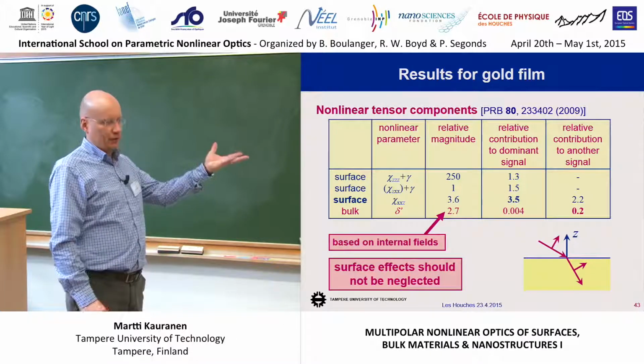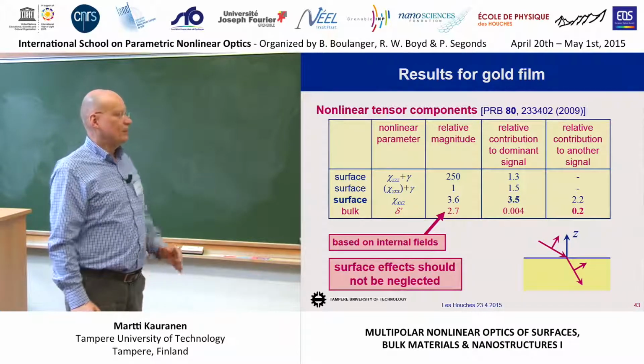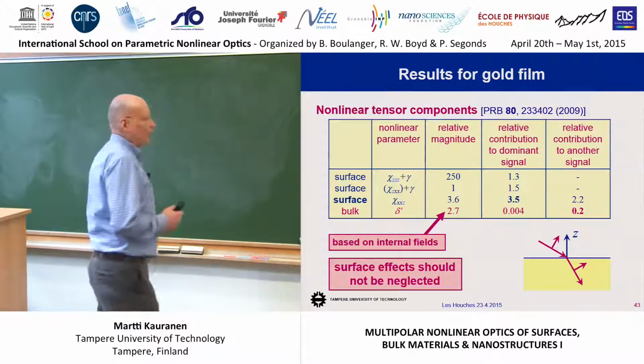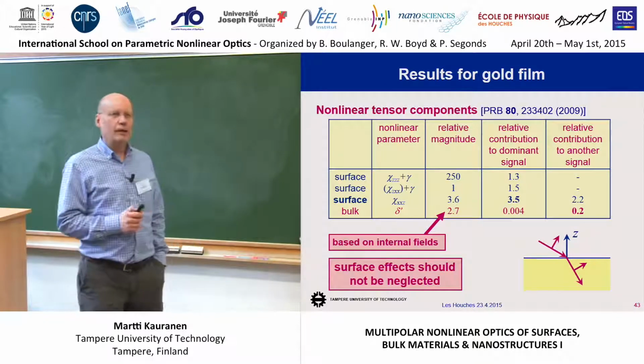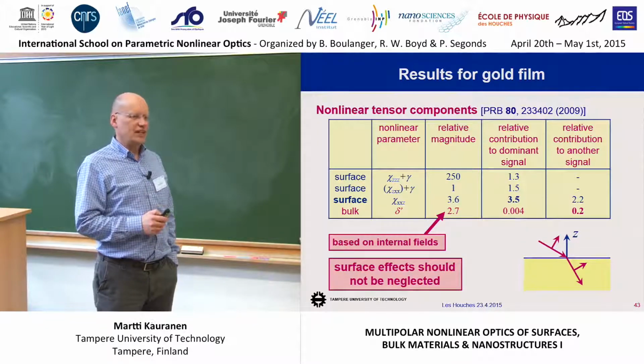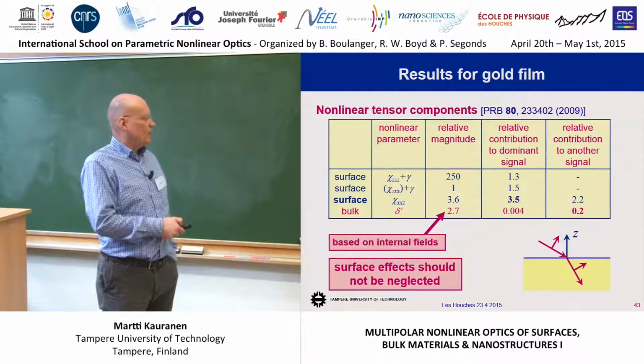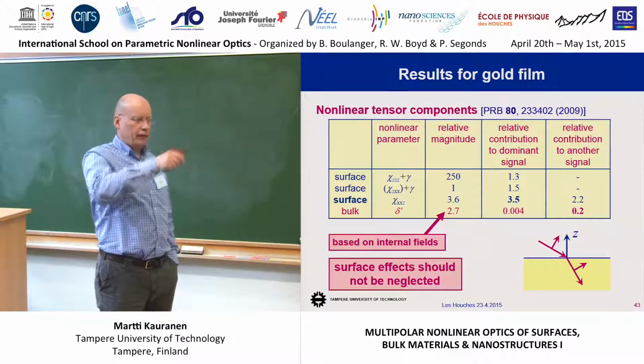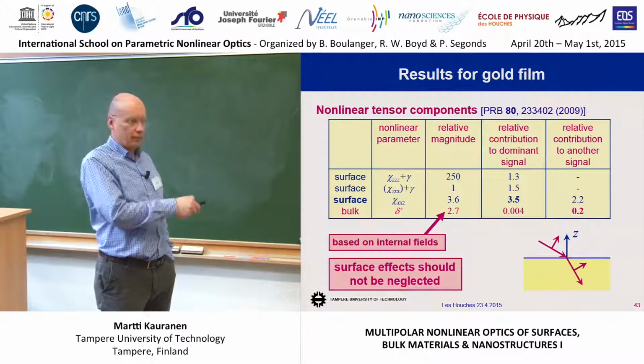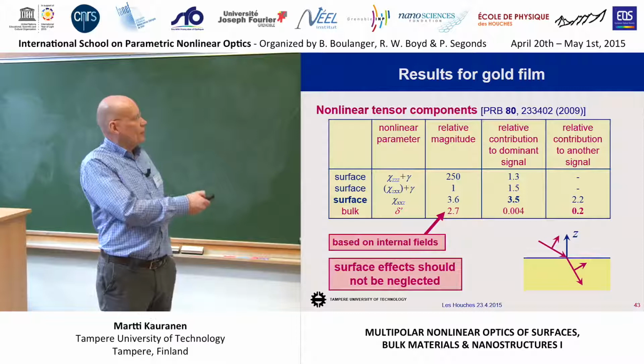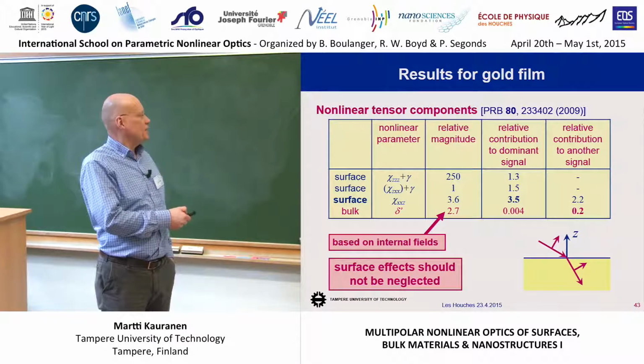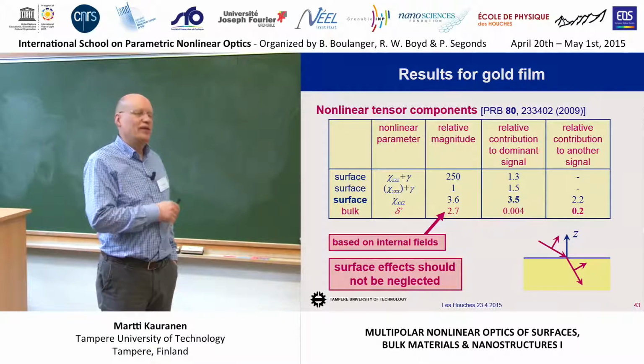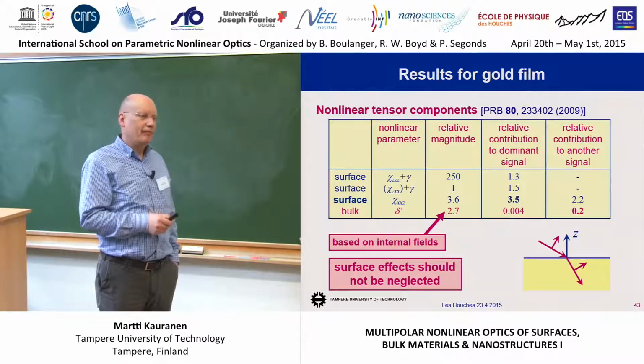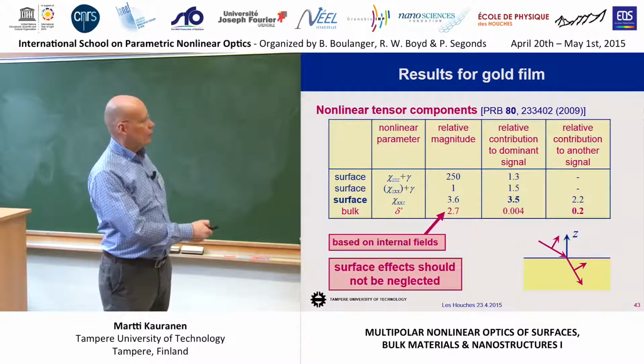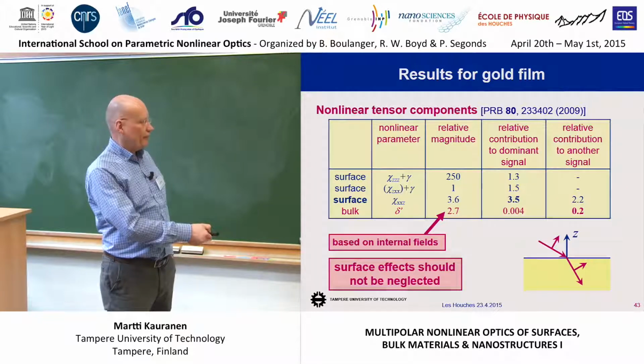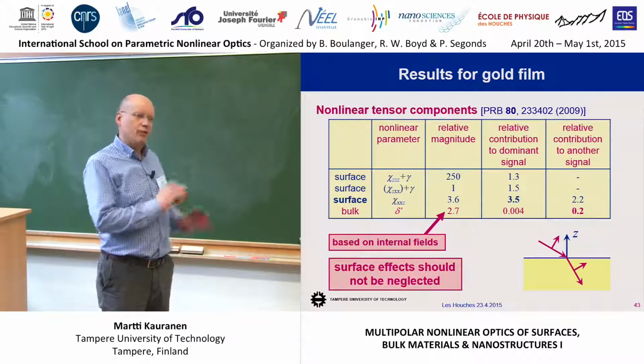You can throw in numbers that say that, okay, this is the dominant contribution. Right now, people who are doing modeling of metal nanostructures, and one way to model is to assume that in a nanoparticle, at each location of the interface, you have this local response, which is described by these numbers. And people are citing this paper of ours, saying that these results show that ZZZ is the dominant component. Yes, we are doing that ourselves, and we can fit our data there very nicely, but the bottom line is that when you look at what we get for a flat film, things can be very different. So you have to be really careful.